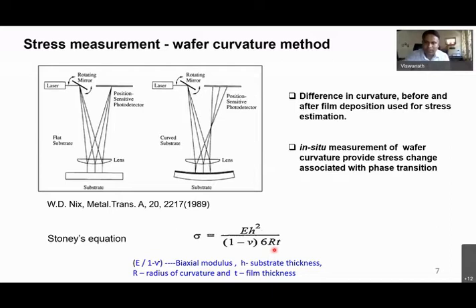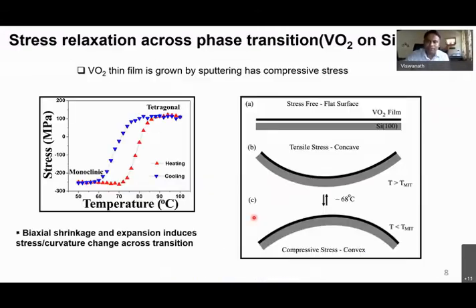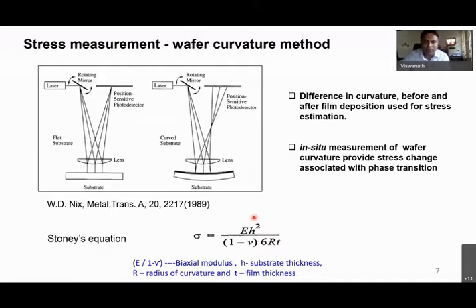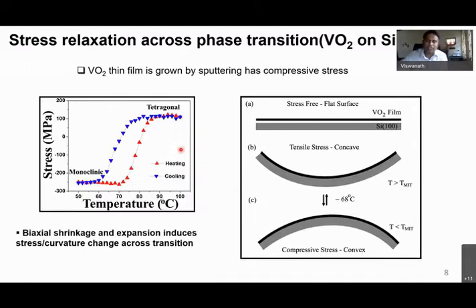So once we know the film thickness and substrate thickness, the radius of curvature is something we are measuring. We have a biaxial modulus. We can measure thin film stress directly from this particular method. The key here is that this measurement can also be done as a function of temperature.